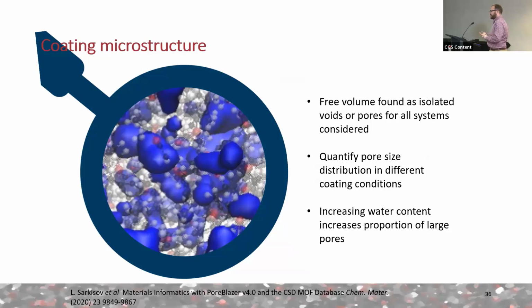So for all the systems I looked at, so all the temperatures, all the cross-linking, all the water percentages, they all had this similar structure of isolated pores. So there was no sort of continuous interconnected network.